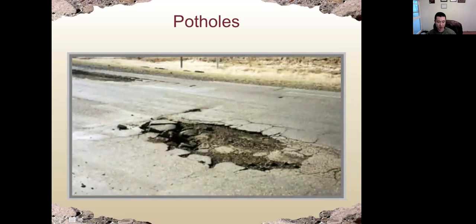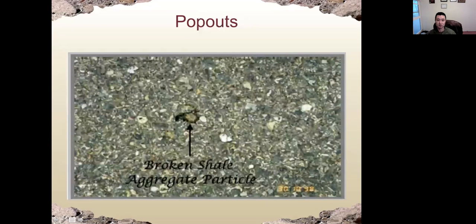This is potholes. And the final picture shown here is a pop-out. Some of the aggregate is reactive, similar to what we discussed in ASR, the alkali-silica reaction between aggregate and Portland cement concrete. So in asphalt pavement, some aggregate may also be reactive, which causes expansive cracking, and it may pop out from the concrete.